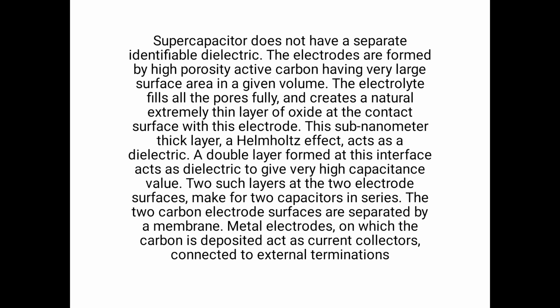A supercapacitor does not have a separate identifiable dielectric. The electrodes are formed by high porosity active carbon having very large surface area in a given volume. The electrolyte fills all the pores fully and creates a natural extremely thin layer of oxide at the contact surface with this electrode. This sub-nanometer thick layer, a Helmholtz effect, acts as a dielectric. A double layer formed at this interface acts as dielectric to give very high capacitance value. Two such layers at the two electrode surfaces make for two capacitors in series. The two carbon electrode surfaces are separated by a membrane. Metal electrodes on which the carbon is deposited act as current collectors connected to external terminations.